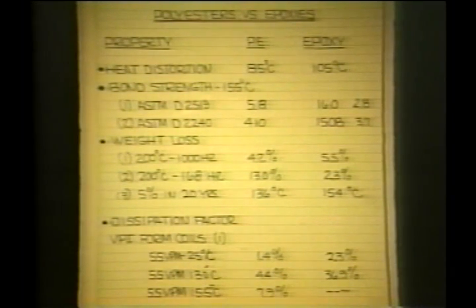However, as I pointed out before, bond strength is a two-edged sword. You want high bond strength, but if it's too high, then if the bond strength of the material is too high, it becomes vulnerable to cracking. And because of its high bond strength, when it cracks, it can also crack the insulation composite materials underneath. Another key comparative point is weight loss, because being an organic material subjected to high temperatures over a period of time, it does lose weight. And obviously one does not want a material which is going to suffer great loss of weight during the normal life expectancy of the system.